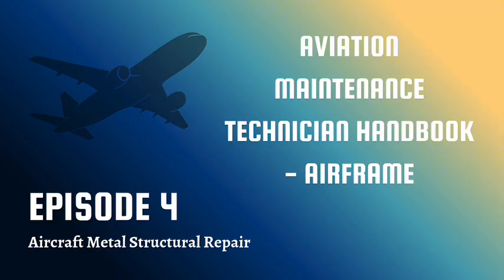Okay, meticulous setup. Finally, let's talk inspection and compliance. When damage occurs, inspecting just the damage spot isn't enough, is it? Absolutely not. Forces travel. You need to inspect the attaching structure well beyond the obvious damage. Look for signs that the impact or stress was transmitted further into the airframe. What kind of signs are we looking for? Things like wrinkled skin nearby, fastener holes that might be slightly elongated, popped rivets, or the telltale sign of movement in a riveted joint. Smoking rivets.